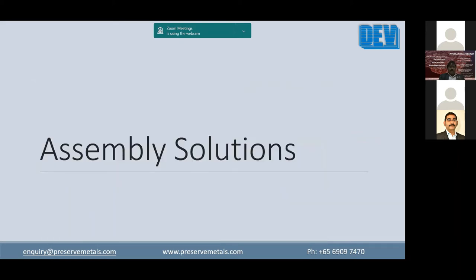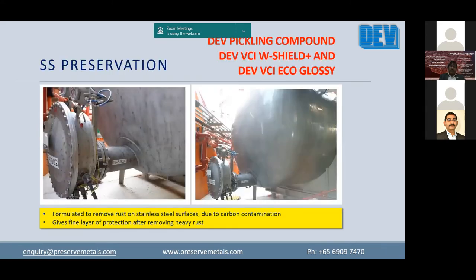Similarly, coming to the assembly solutions. For example, during the assembly stage, it is quite common to see stainless steel piping and vessels being contaminated, and then localized rusting happens as if it were carbon steel. This normally leads to a significant requirement for pickling and passivation. With the traditional method of pickling and passivation, the problem is that residual contamination can still pop up after 3 months or 6 months, and cause claims and repair rework during the warranty period at a prohibitive cost.